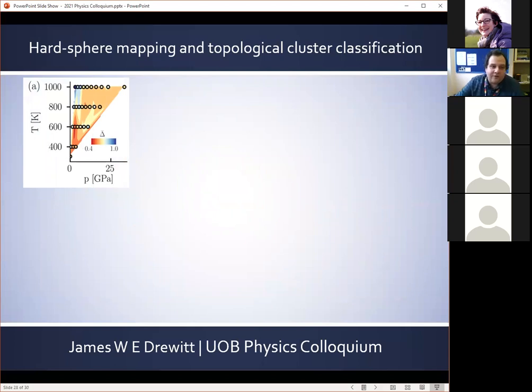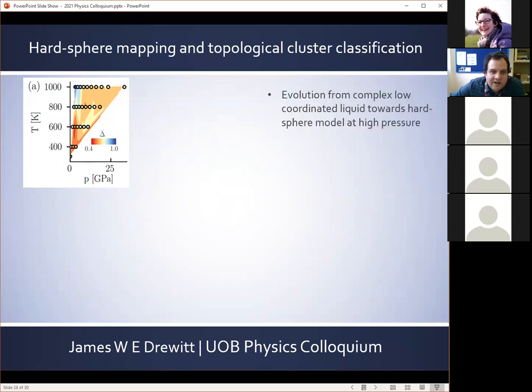And so finally, for every ab initio molecular dynamics data set, Francesco developed a scoring function, here delta, which describes the deviation of the ab initio simulation from a hard sphere structure. And so the blue color represents the largest deviation from hard sphere structure, and the orange and red simulations are closer to hard sphere structure. And so as indicated in the measurements, the structure tends to resemble a hard sphere-like structure at high pressures and temperature towards the melting curve. Although the deviation from the simple model remains very high, above 40% over all pressure-temperature space.